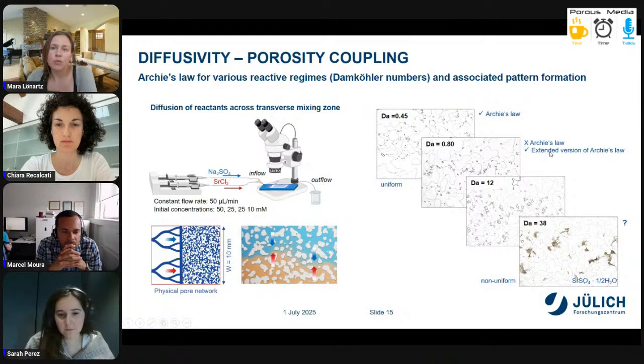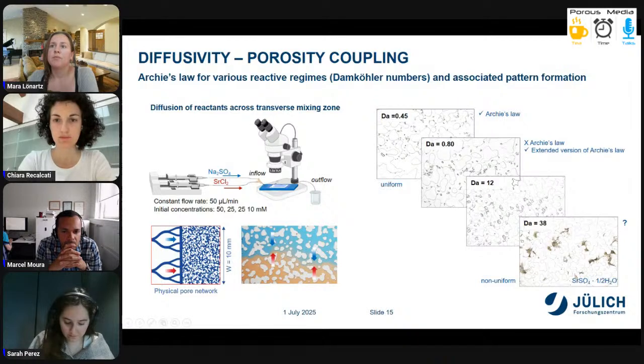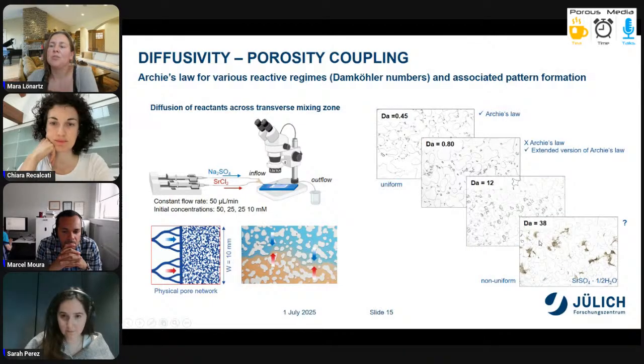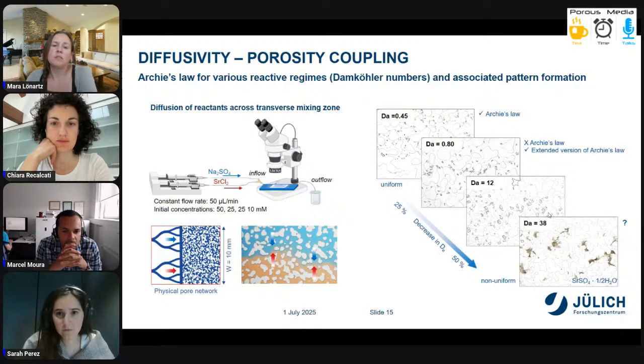The extended version, I refer to the additional fitting parameter, was working out in this case. But for the case of the intermediate phase precipitation, it was pretty tricky to find an equation or relationship that really captures this phenomenon, and still leaves behind a question mark regarding how long this state is still present, if we think about the redissolution of this intermediate and metastable phase and the reprecipitation of the water-free phase of celestine.